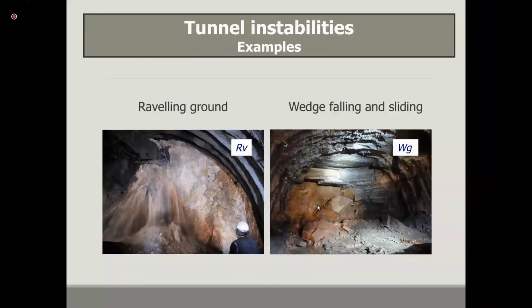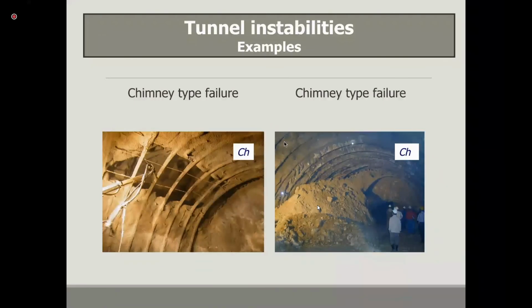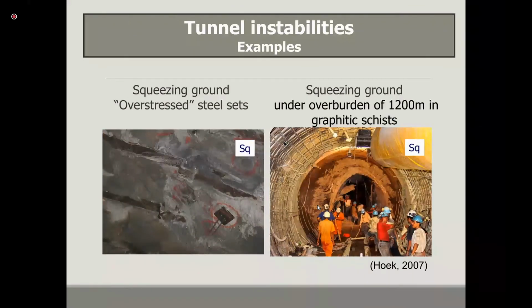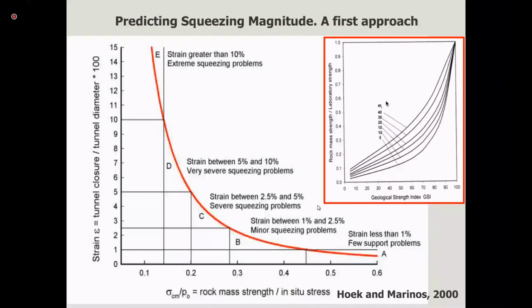So some pictures of raveling ground or wedge falling and sliding, and chimney type failure, and you see here the material that has over-excavated and fallen. In this particular case, this is a completely weathered gneiss at depth along a fault zone, and of course the squeezing ground and overstressed steel sets. You can see here how all these are yielded, and the very famous picture on the right side. Again, you can see in a hydraulic tunnel how this has squeezed. And a first approach, let's say, for when we start to have these stress controlled failures, is this chart coming from Hoek and Marinos 2000.